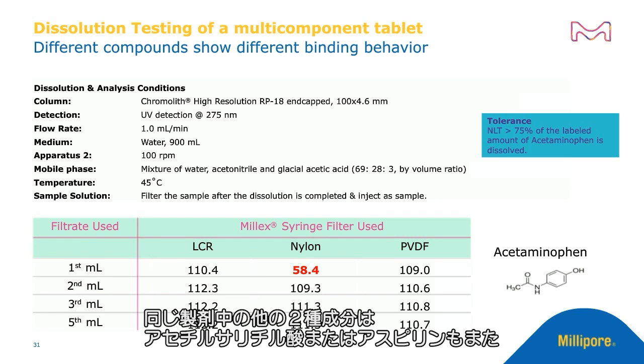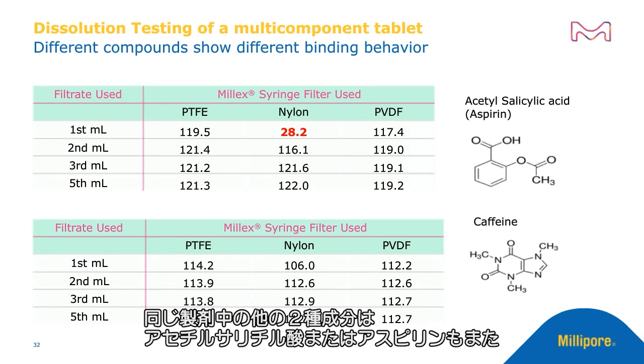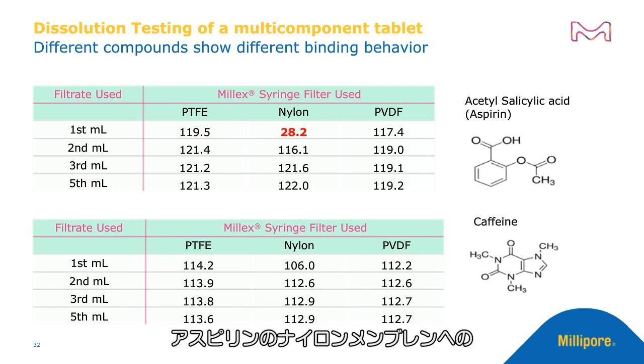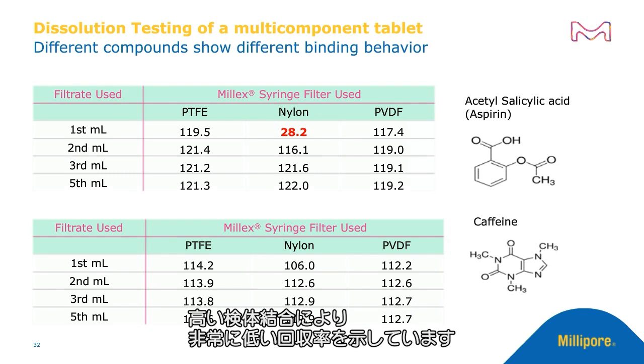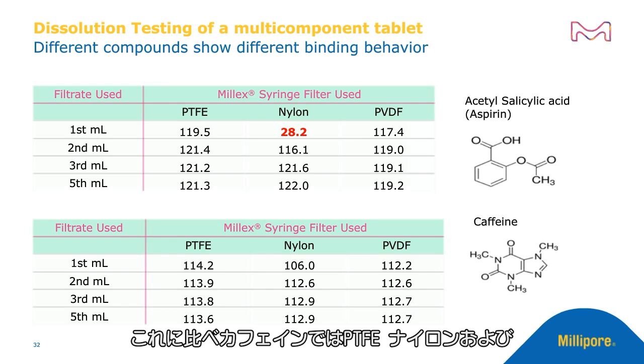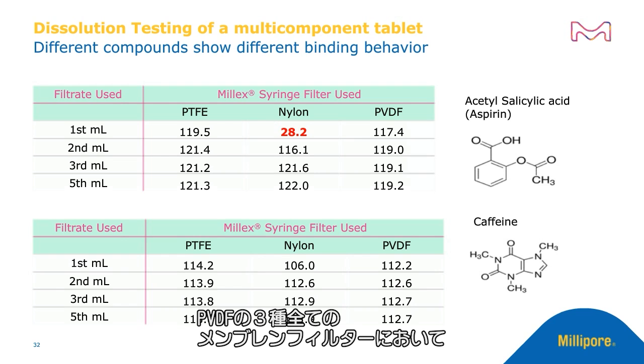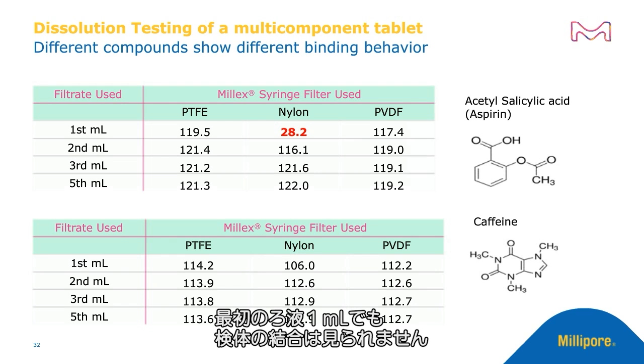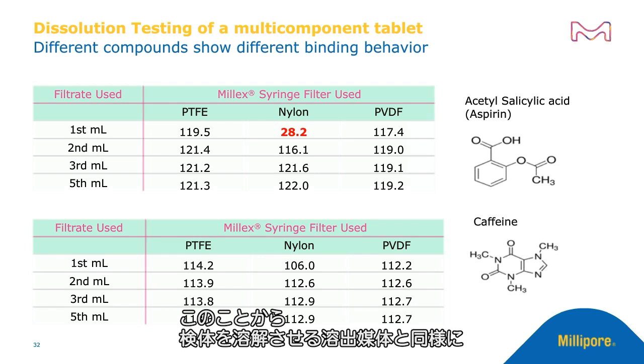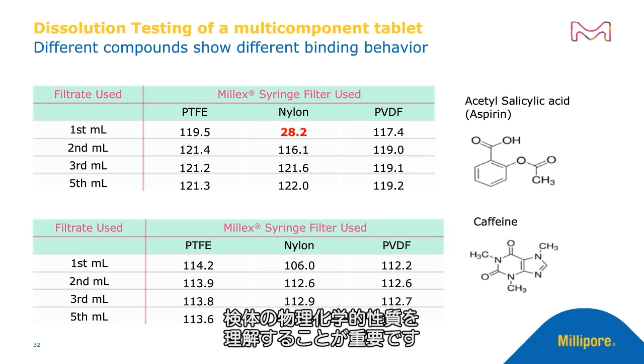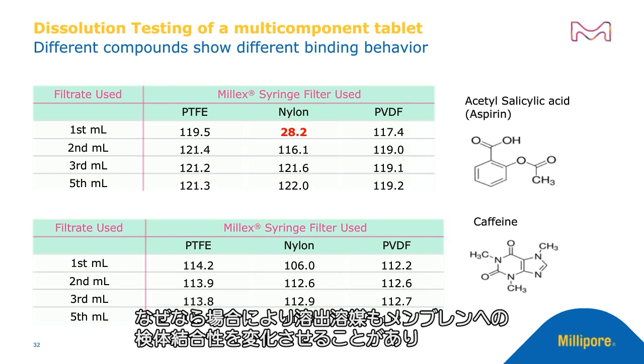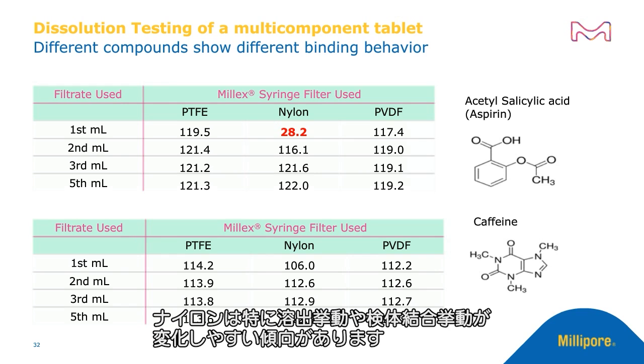For the other 2 components from the same formulation, acetyl salicylic acid or aspirin again shows very low recovery due to high analyte binding of aspirin to nylon membrane. Compared with that, for caffeine, all the 3 membrane filters, the PTFE, the nylon, as well as PVDF, do not show any analyte binding even for the first ml of filtrate. So it's important to understand the physico-chemical characteristics of your analyte as well as the dissolution medium in which the analyte needs to be dissolved, because sometimes even the dissolution medium can change the analyte binding to the membrane. And nylon is more prone to this dissolution behavior and analyte binding behavior.